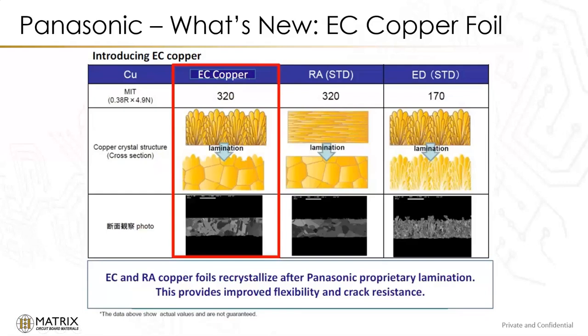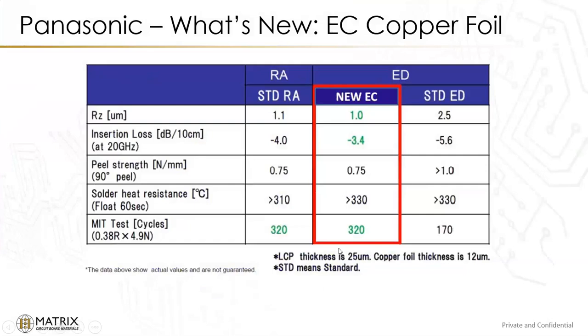Some of the properties about that, you can see that it has a low Rz value. We'll talk a little bit more about that compared to the standard electrodeposited foils. The insertion loss is lower. Peel strength is still comparable with that, very good. It's comparable especially compared to the RAs, which are difficult with that. Heat resistance is improved, and then the test cycles are the same as the RA. So we get good performance and good crack resistance with the EC foil with it.